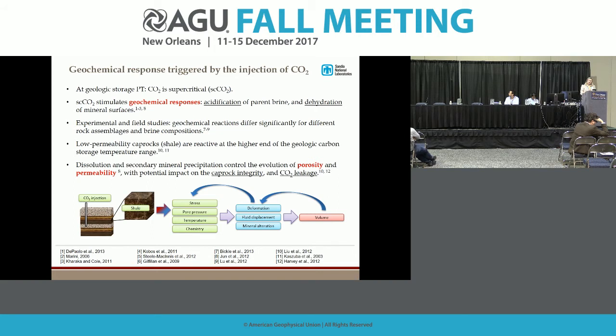At geological storage pressure and temperature, CO2 exists as a supercritical phase, and when it's injected underground, it can set off a series of different reactions, including chemical and physical, because it perturbs the steady state of the system. And so the perturbation includes changing the state of stress, pore pressure, temperature, and chemical reactions. The two most typical chemical responses are creation of carbonic acid, acidification of brine, and also dehydration. So when CO2 is injected, it's completely dry, and as it moves underground, it picks up those water molecules and dehydrates the parent mineral assemblage. That can affect porosity and permeability.